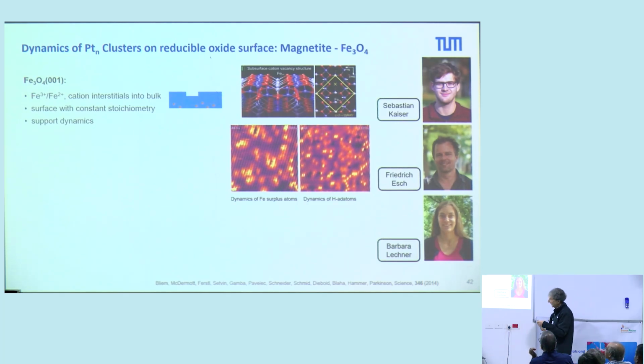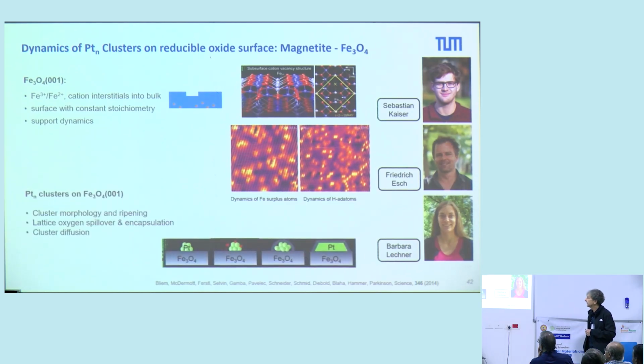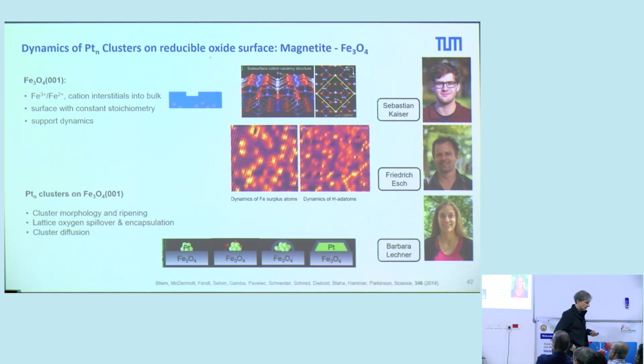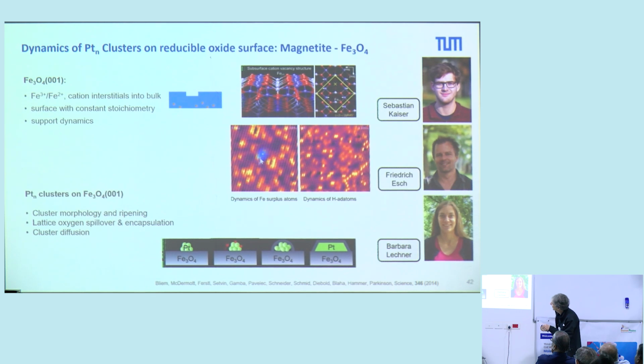You also have a dynamics. You have iron atoms that can diffuse on the surface, and if you have hydrogen, you can also have diffusion of hydrogen on the surface. But this is not our interest. We use these support materials as a support of size-selected clusters. And we're depositing platinum clusters on these surfaces, and our interest was in the dynamics. What is the video? This is the iron plus. You see other videos. These are iron atoms that are moving on the surface, and here you see hydrogen atoms on the surface. STM? STM, yes. It is fast STM. This is one of our specialties. We have a fast STM. We also have atom tracking. I will show you some videos later.